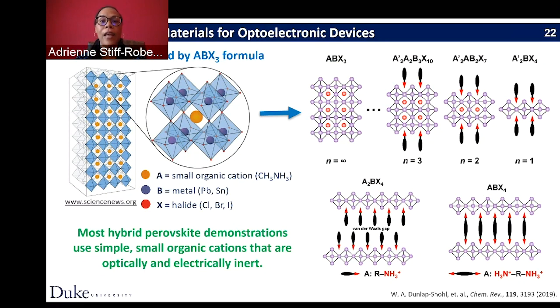They're not really participating in the overall properties of the material. So if you go to larger organic molecules, you can introduce functional molecules, things like dye molecules that are actually participating in what the optoelectronic properties are of the material. And so you can introduce these organic materials, and they give you essentially what can be a self-assembled quantum well. So as you increase the amount of organic molecules that you have, you create these layers of inorganic layers. And so you have a self-assembled quantum well of the organic and inorganic layers.